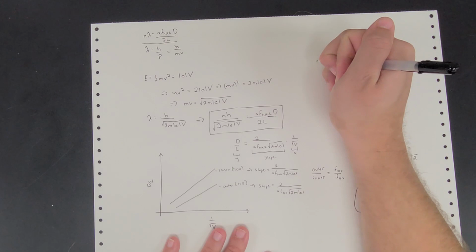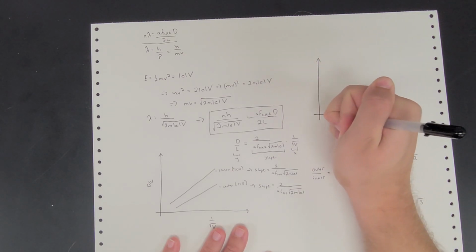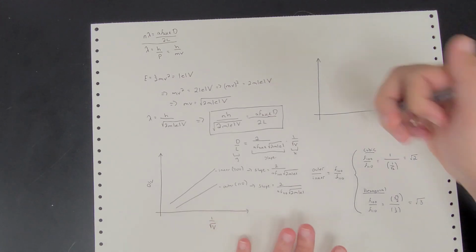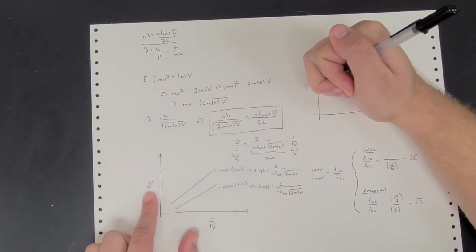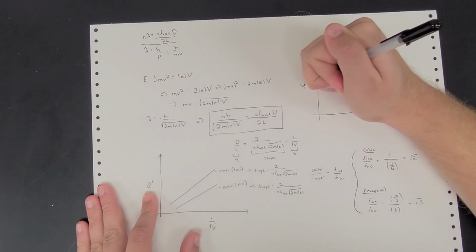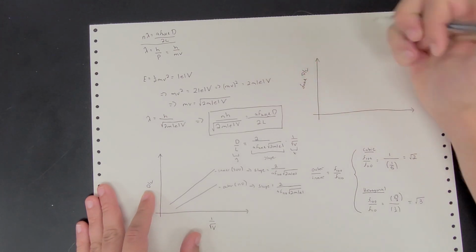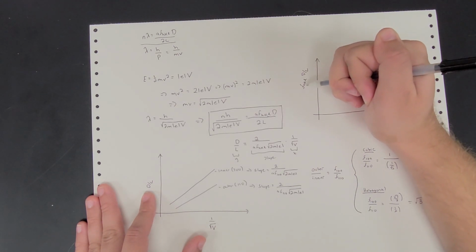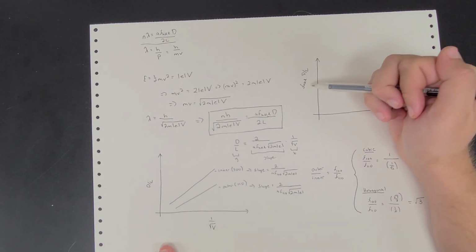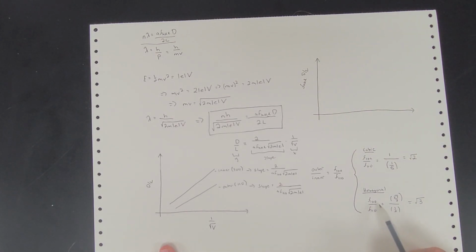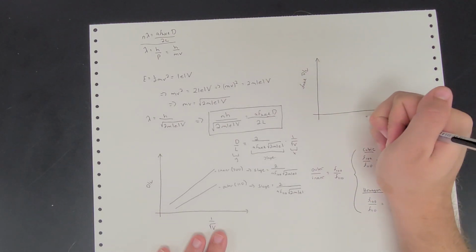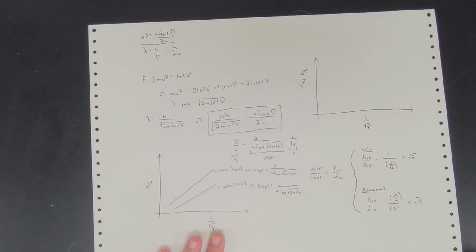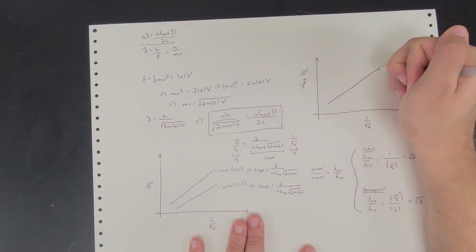Okay, and in doing so, we can create another graph, but this graph will only have one line, where on our y-axis, instead of graphing d over L, we're now graphing FHKL times d over L, where we take the corresponding FHKL values and multiply it by the corresponding diameter. So make sure that for the inner, you're using the FHKL for 100, and for the outer data, you multiply it by the FHKL for the 110. Okay? And then for our x, we're still going to have 1 over the square root of V. And so we're going to have some graph here.